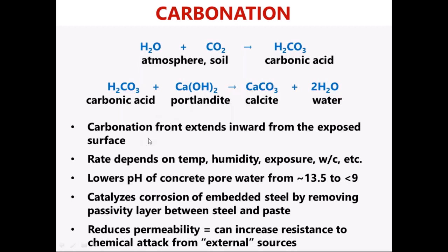And the rate at which carbonation occurs depends on a lot of factors. It depends on temperature and humidity, interior versus exterior concrete, the water cement ratio of the concrete, everything. So it's impossible to say how fast carbonation will grow or extend into the concrete from the surface that's exposed to the atmosphere.